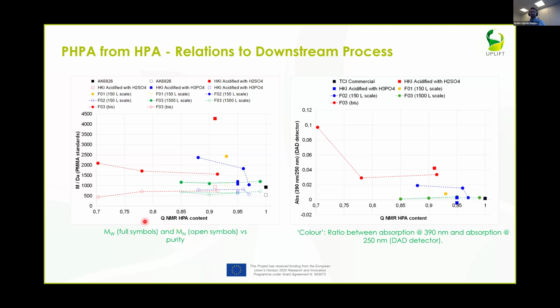And what you can see here on the x-axis is the purity of the system, and out here you can see the molar mass for these. These are not high molar mass polymers, which really doesn't matter for the point that I'm trying to make here. But what you can see is that purity is actually not the decisive factor for the molar mass that we can get from these systems.